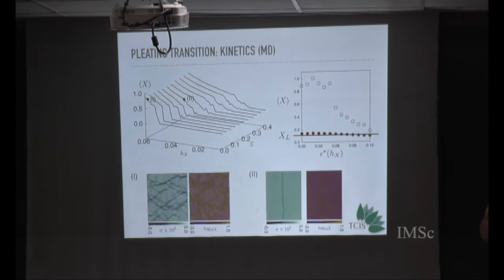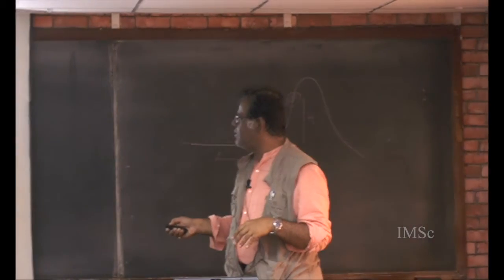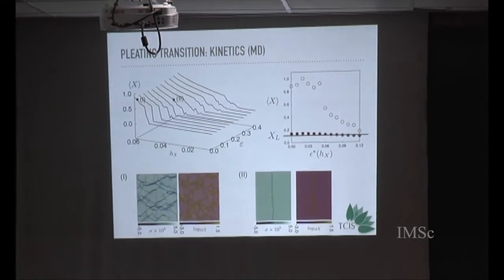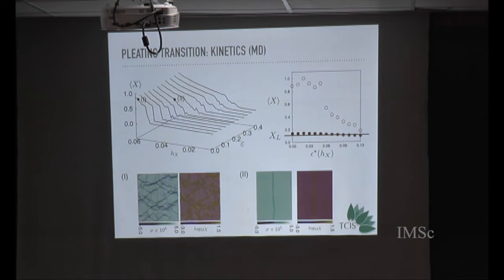Okay, so now instabilities and dynamical transitions. If you have an equilibrium transition, so this much was Monte Carlo. Now we do molecular dynamics. If you do molecular dynamics, you never get these nice patterns, but you get something amorphous. The reason is that it is forever trying to go into these patterns. So these are the ground states, and it is trying to dynamically achieve these ground states, but it is taking an enormous amount of time